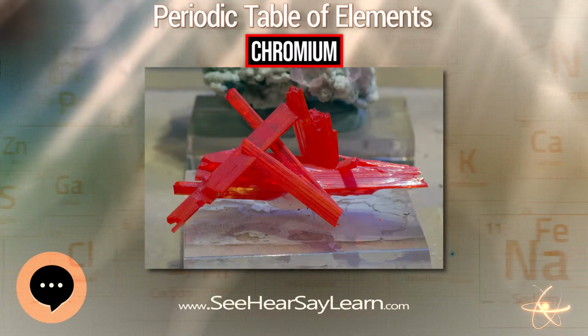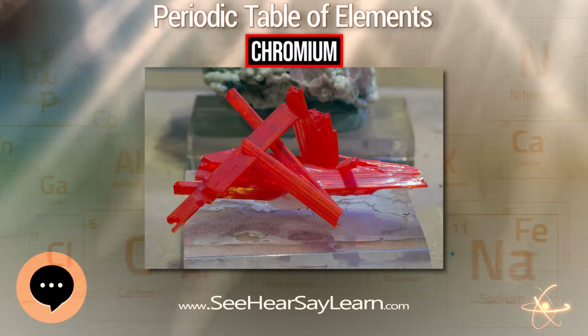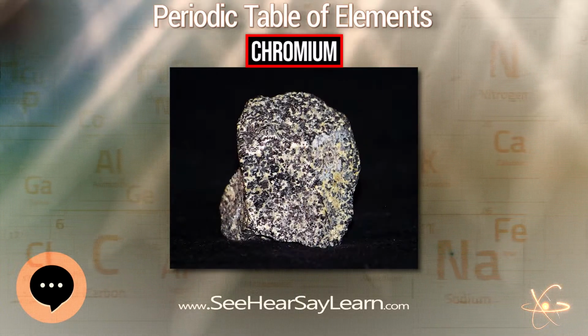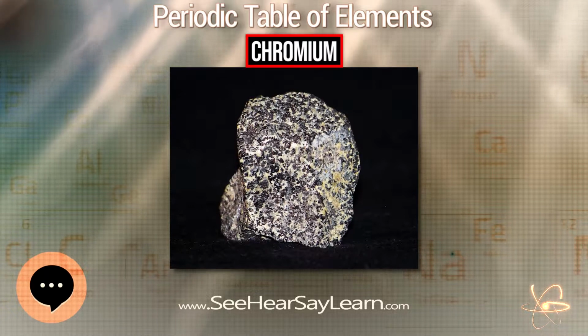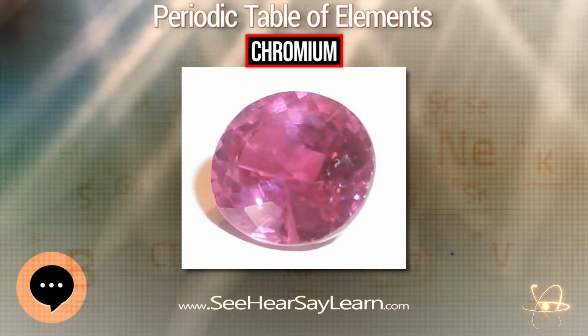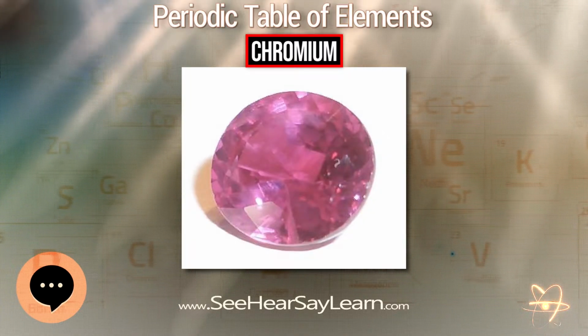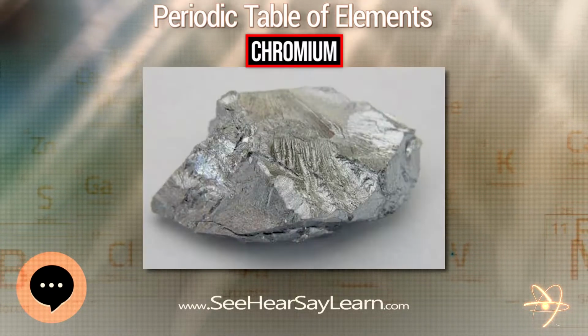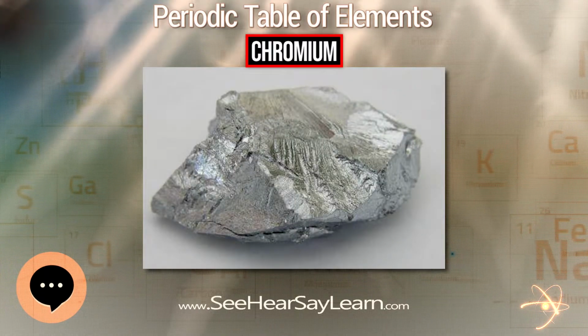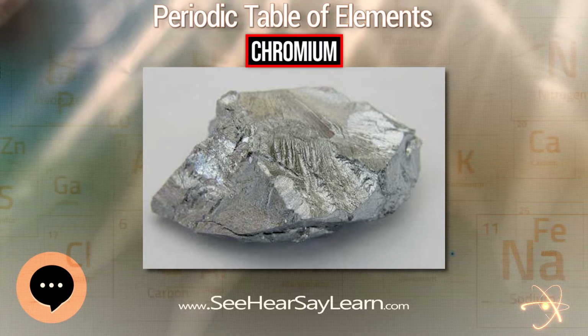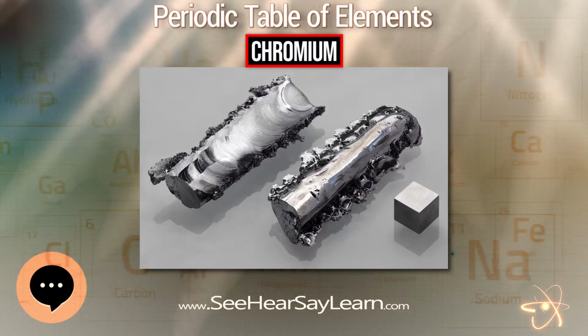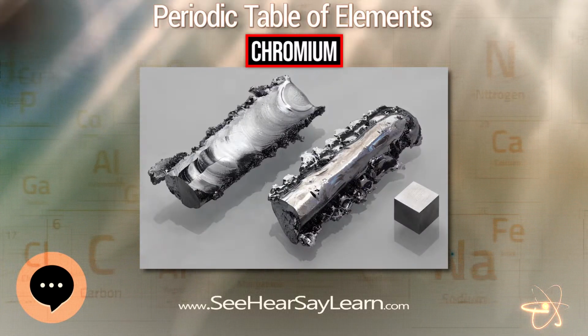The chromate is converted by sulfuric acid into the dichromate. The dichromate is converted to the chromium oxide by reduction with carbon and then reduced in an aluminothermic reaction to chromium. The creation of metal alloys account for 85% of the available chromium's usage. The remainder of chromium is used in the chemical, refractory, and foundry industries.